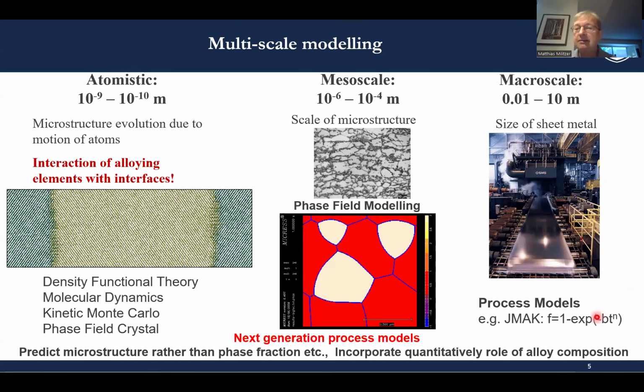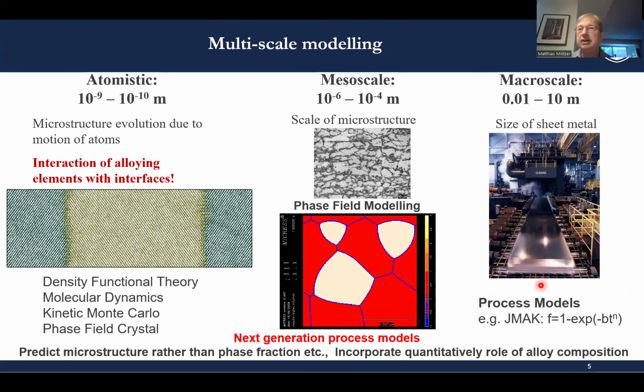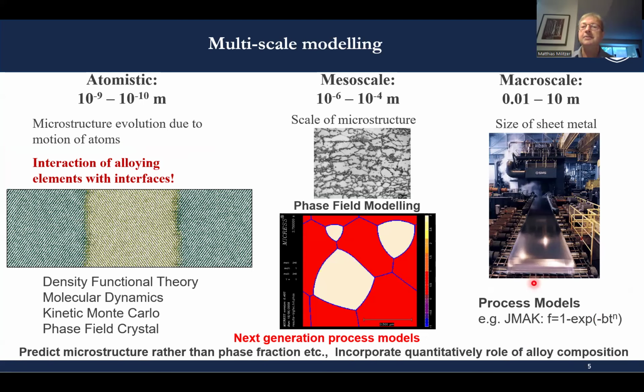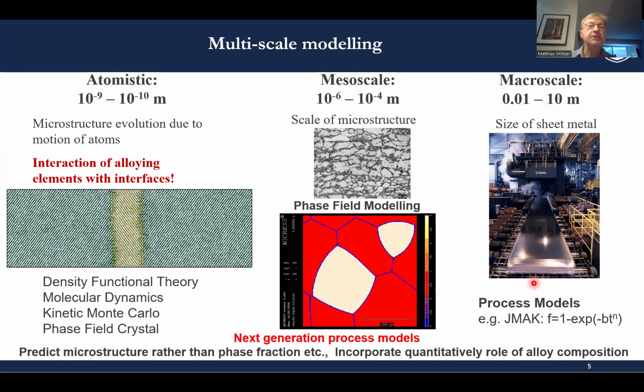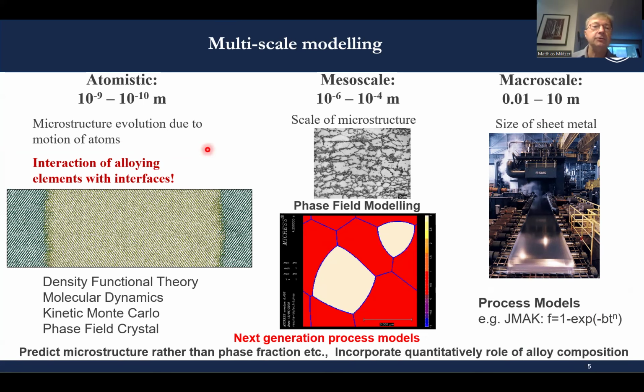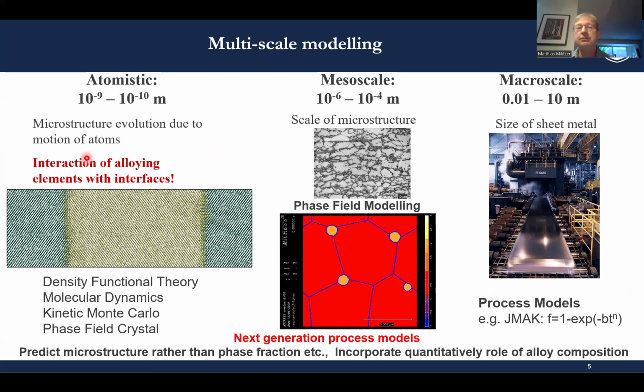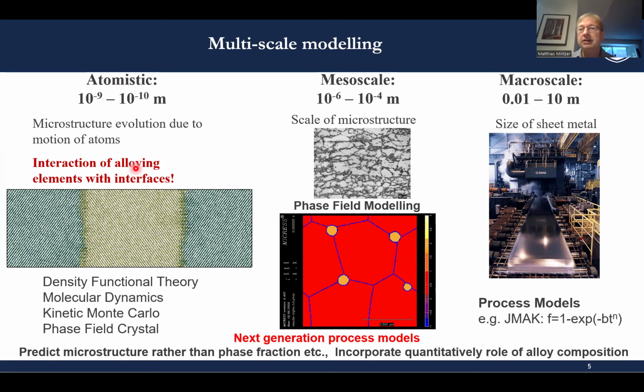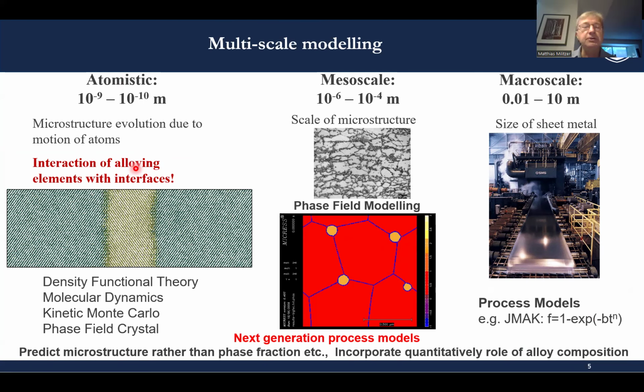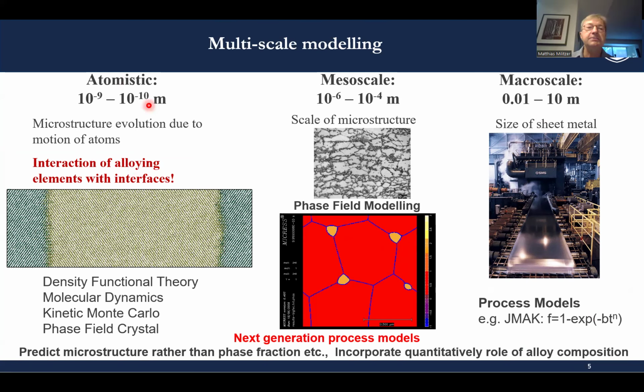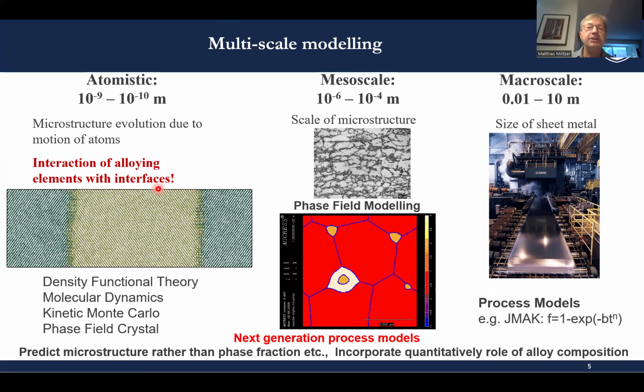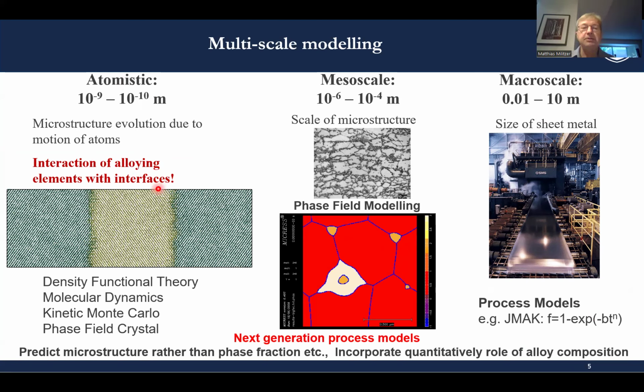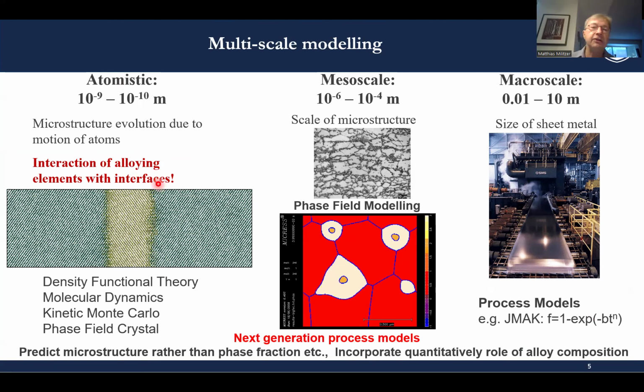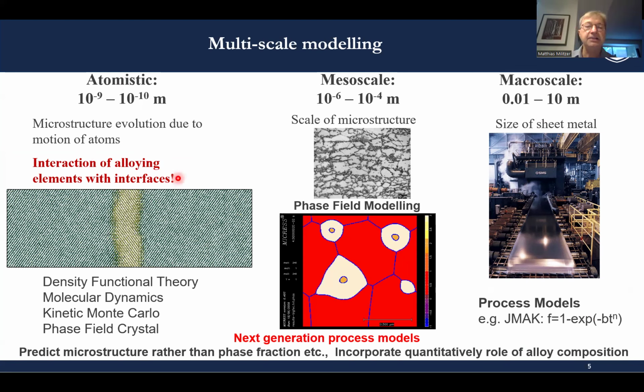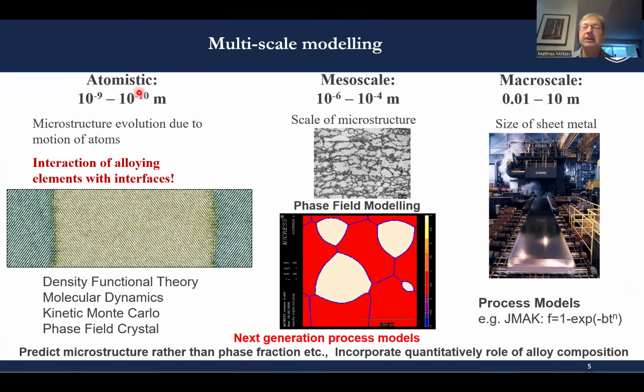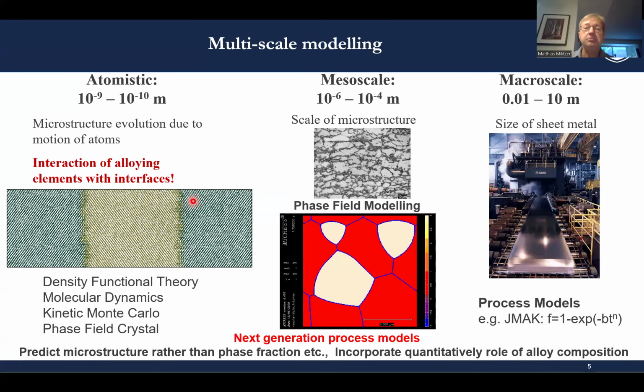But on the other hand, we know that it's the migration of interfaces between different phases or between different grains, i.e. grain boundaries, that determines the microstructure evolution, and that alloying elements tend to interact with these interfaces. If you look at an interface, it's maybe about a nanometer or so, something that happens on the atomistic length scale. And we now have the computational power to use modern computational materials science tools that include tools that can model the atomistic scale, like density functional theory, molecular dynamics, kinetic Monte Carlo, etc.